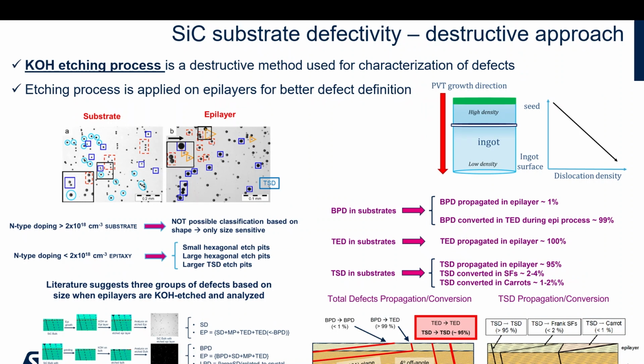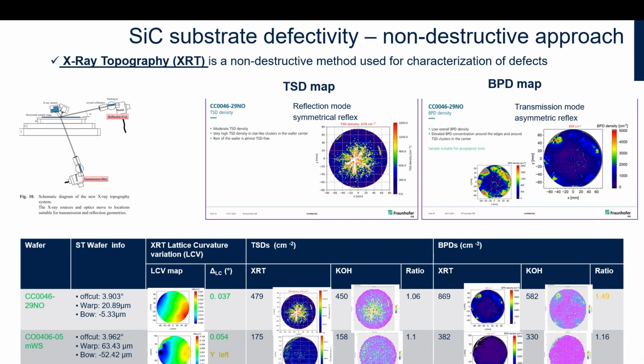And in the substrate, you have to measure the density of dislocations, because you have to achieve a spec. You typically measure it by a destructive method, which is KOH. And of course, you can also have statistics, and it's also very expensive. And more recently, there is an introduction of things like X-ray topography, in order to have a non-destructive manner. But the point is, if you want to manufacture silicon carbide, you have to have a way to control the growth of the crystal and to measure the defectivity, warpage, and resistivity of each and every wafer of the boule.